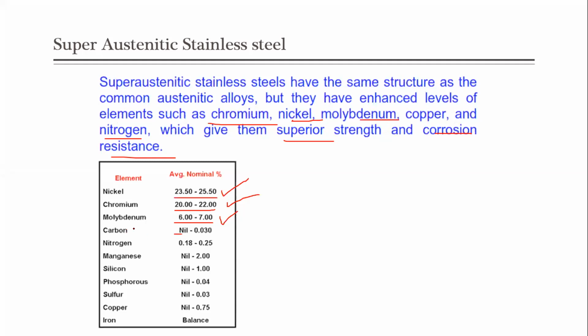And you will have almost nil carbon in super austenitic stainless steel. The maximum amount that you can get will be around 0.03%, and nitrogen will be around 0.18 to 0.25%. In case of 316, you will have nitrogen content around 0.15%, and the rest you can see the rest are nil. If you have any specific application which requires toughness, then you add some amount of manganese also.